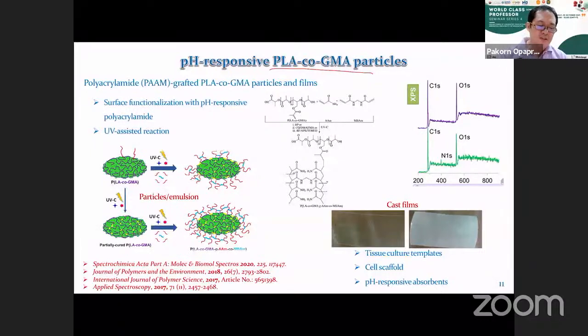So in this case, we show the process of grafting polyacrylamide, which is responsive to temperature and also pH as well. When we are successful in grafting this polyacrylamide on the surface of these particles, we can also use these particles as responsive materials.